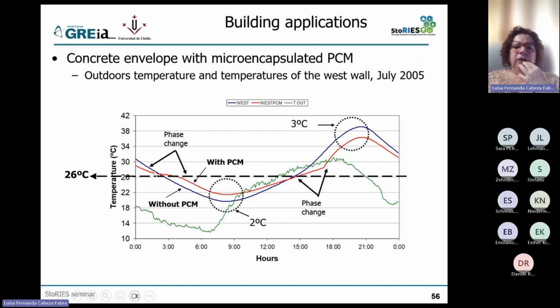And what we were reaching in the red line is that, first of all, there are these nearly horizontal lines, which is when the phase change material is melting. That means that the temperature range between the minimum and the maximum inside the building is lower. This is when we approach thermal comfort. And also there is a delay of the maximum temperature. Here I reach 34 degrees 3 hours later than when I don't have PCM. This is the thermal inertia effect that I was showing you. It's not only decreasing the peak temperature, it's also having a given temperature later in time.